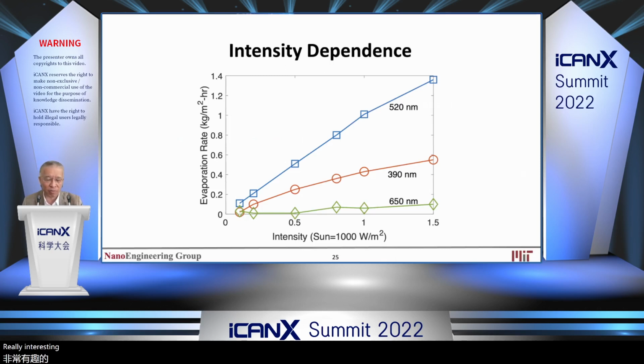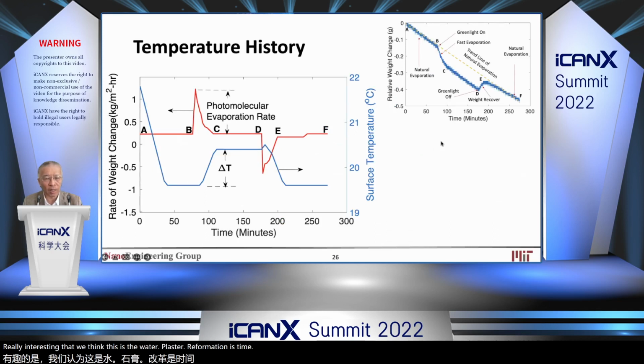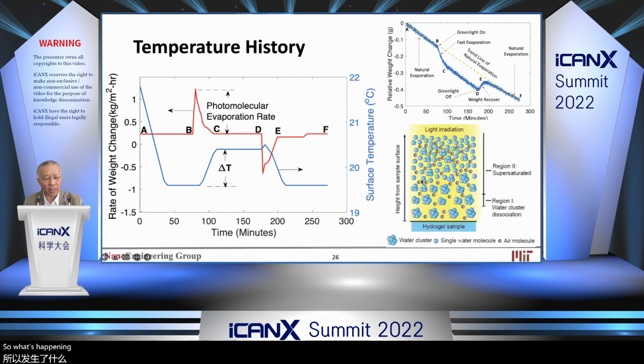It's really interesting, because we think water cluster reformation needs time. And the temperature history: at the beginning, when light turns on at B, you have fast evaporation. Then we look at the temperature history on the surface, the blue curve. First, natural evaporation, the temperature drops below ambient. When light turns on, you can see between B and C, the rate decreases, but the temperature increases. So what's happening? And this is the same picture.